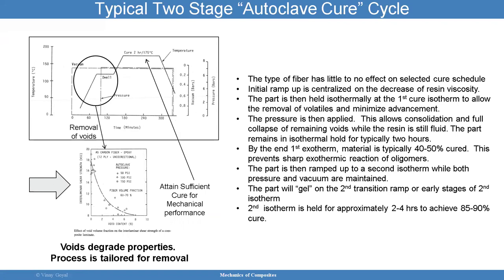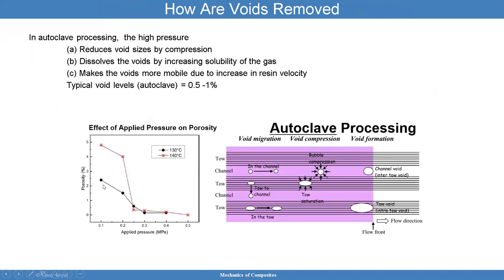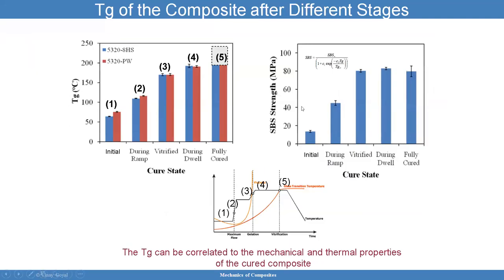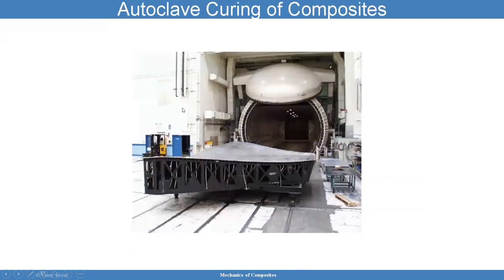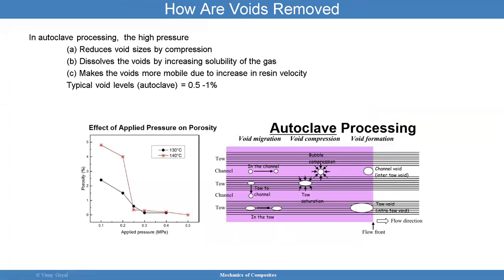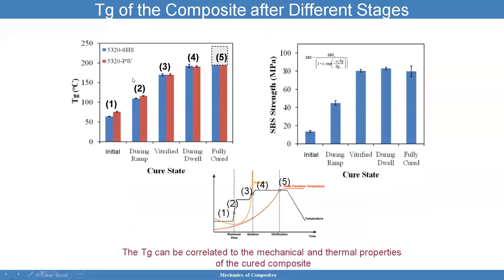A typical two-stage autoclave cure cycle, I do want to point out that voids, this kind of porosity, will decrease the mechanical properties of the material. So not only can a lower Tg result in lower properties, the number of voids within the structure can also decrease the strength. And that makes sense because if in stage one suddenly the whole thing stops operating, well, the whole point of stage one was to remove voids. But if in stage one everything stops operating, then I'll have voids, and voids are stress concentrations. And I was not able to get rid of the stress concentrations. So those stress concentrations decrease the strength of that laminate that I'm curing.